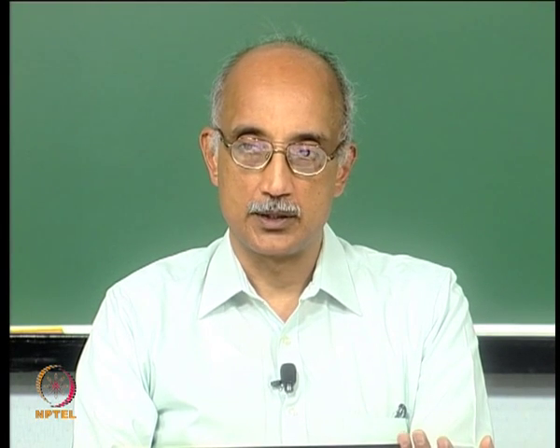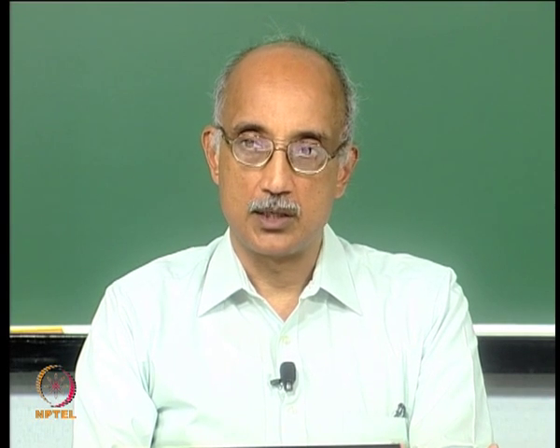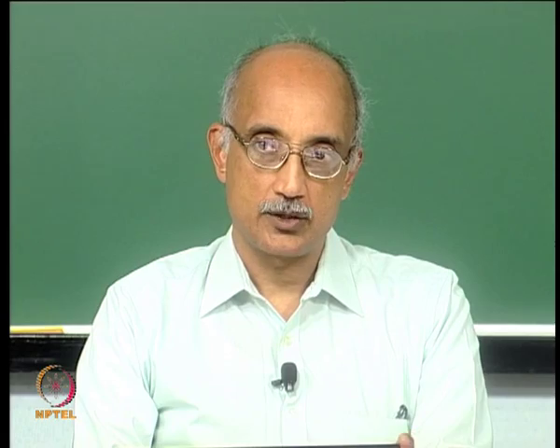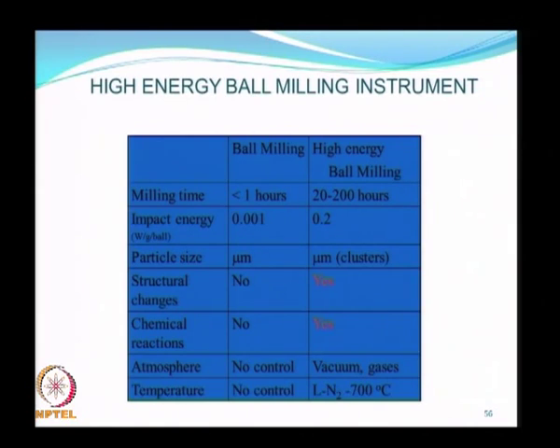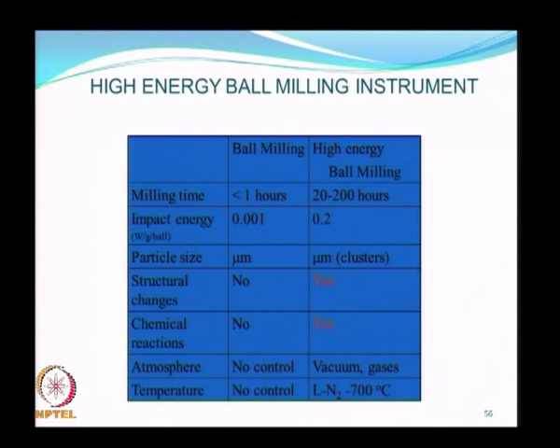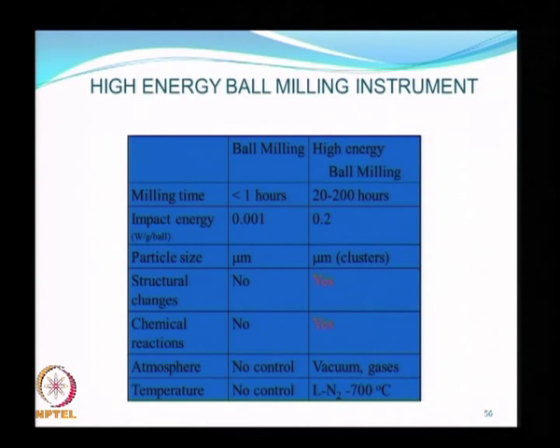If you want to synthesize metal nanoparticles without oxide contamination, you must provide an inert environment. One of the key differences in a high energy ball mill is that you run the mill for much longer—the mean size keeps decreasing as the mill runs longer. While a conventional ball mill achieves particles of around 10 microns mean size in one hour or less, a high energy ball mill achieves much smaller sizes simply by running much longer.